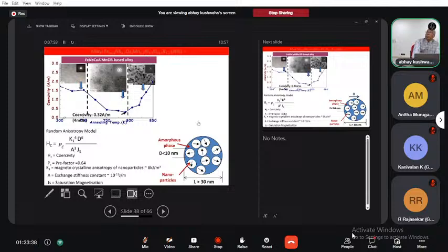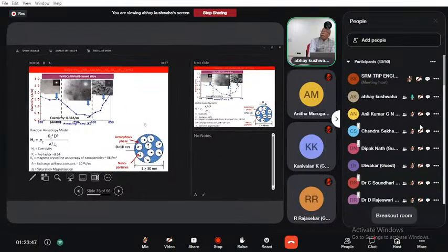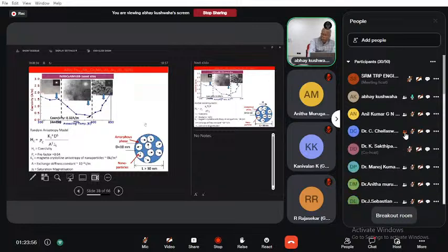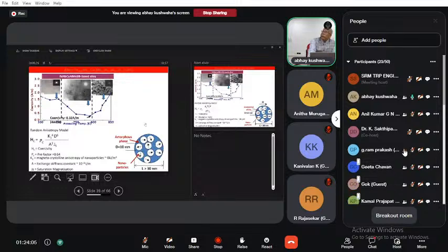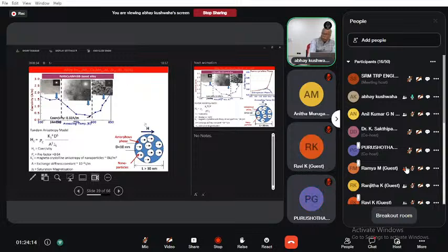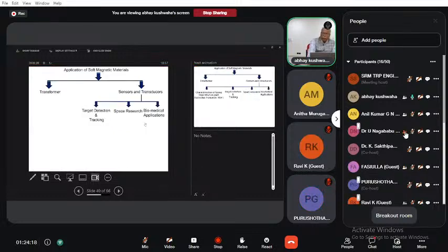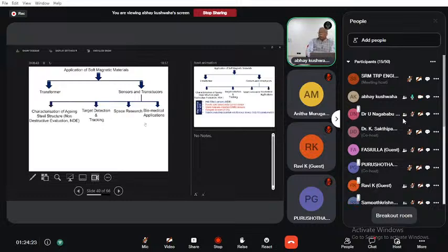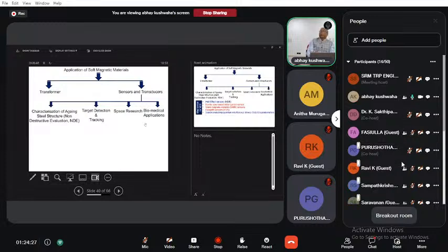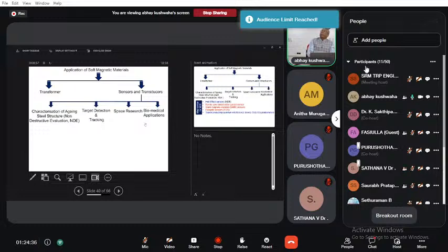And here you can see the coercivity reduces with the grain size d to the power 6. So what has happened here, basically, is that within one domain wall width you have a large number of nanoparticles, and by application of a small field the domains rotate along the magnetic field. So this process takes place at such a small field that the coercivity becomes very low. This is also used for development of small transformers, and its application is in different types of sensors, because its coercivity is extremely low. Extremely low coercivity indicates that its permeability is extremely high.